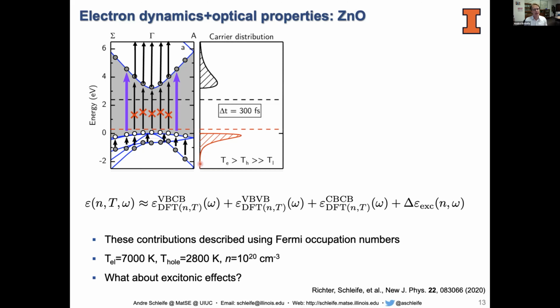And then you get transitions. These are two sets of transitions. One is indicated down here, which are transitions within the valence bands, because you emptied up those states, so you can now get transitions there, and you get transitions in the conduction band states from these lowest occupied ones into higher ones. Those contributions need to be all accounted for if you're looking at time-resolved studies.